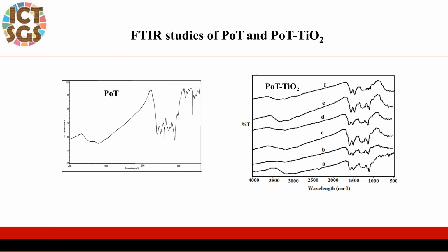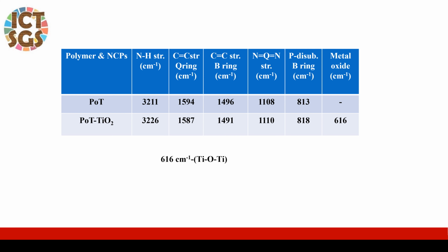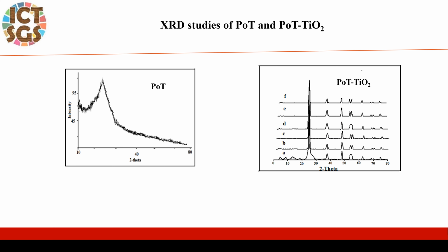FTIR spectra of PoT and polymer metal oxide nanocomposite have been seen in this figure. These characteristic peaks indicate the polymer, and these peaks also indicate the polymer metal oxide nanocomposite. Specifically, 616 per centimeter indicates the titania oxygen titania symmetrical stretching frequency. X-ray diffraction patterns were recorded for polymer and polymer metal oxide nanocomposites.